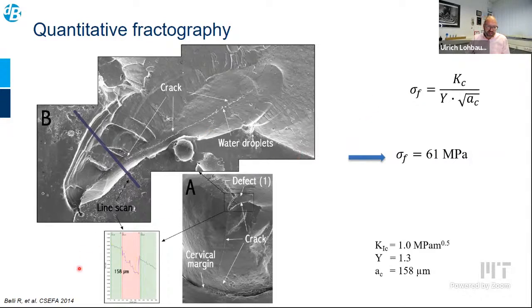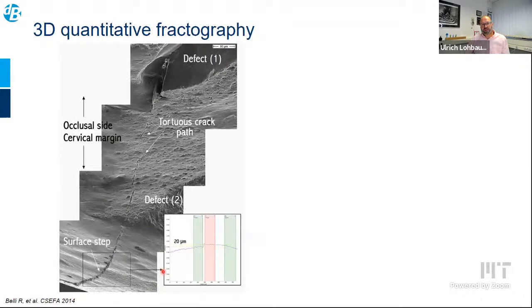So this is assisted, of course, by profilometric techniques. It's also three-dimensionally measured. And this is another example of what we did. We have seen this is a crown, the margin of a crown down there. And you see not only the crack that is starting from down there, going up to the cervical part of the crown. But there is also a shift of the two surfaces, and this is an indication there is something here, 20 micrometer shift in the material.